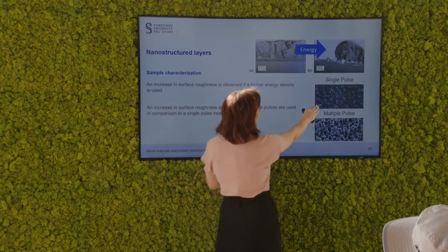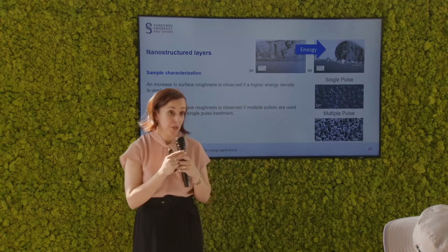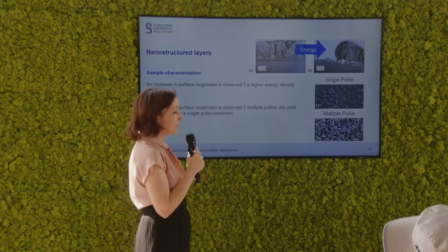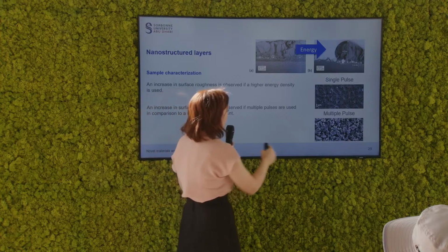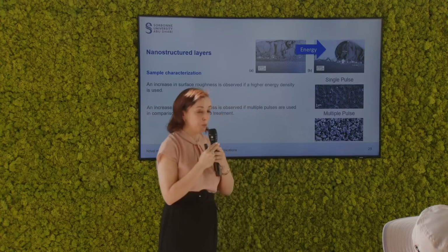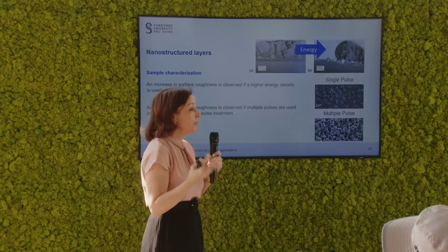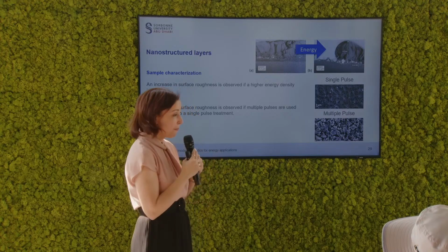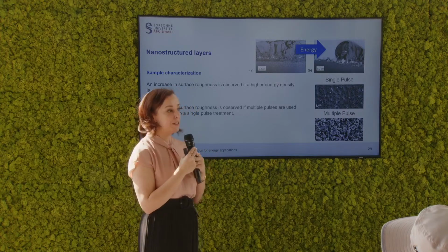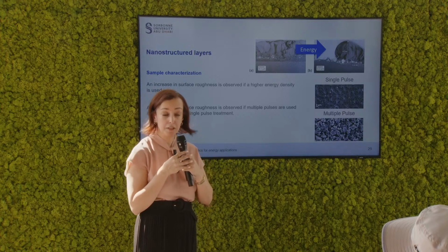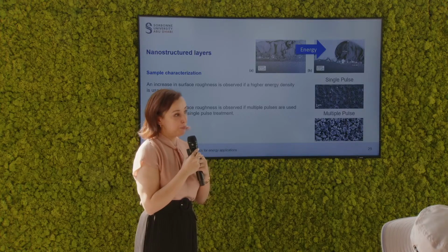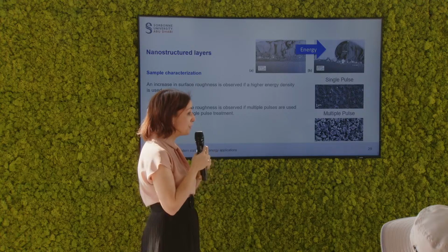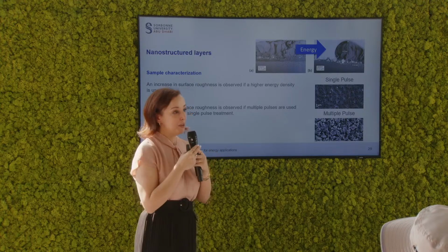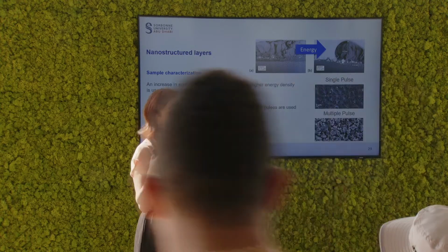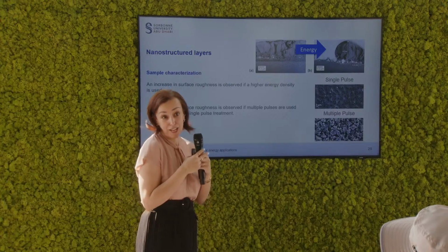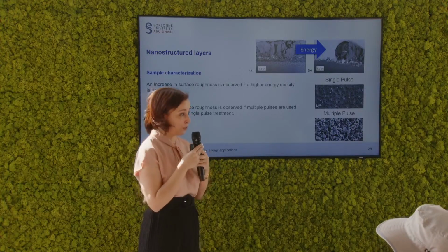This image here shows you the single pulse treatment, which has a surface roughness but is not as high. And you will see here in the lower image, the multiple pulse treatment, in that case, generates a large surface roughness. Now, surface roughness is not necessarily something that a lot of applications would like. However, for our particular application, this is quite efficient because you can control the amount of surface roughness, and therefore you can nanostructure your layer using the simple laser pulse.